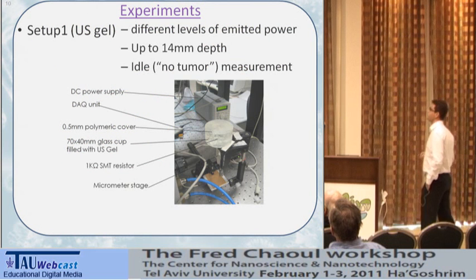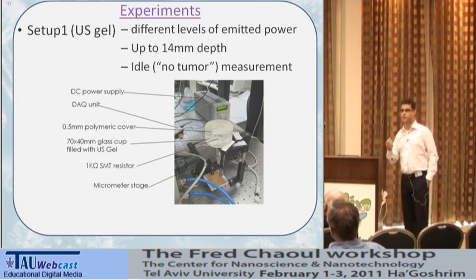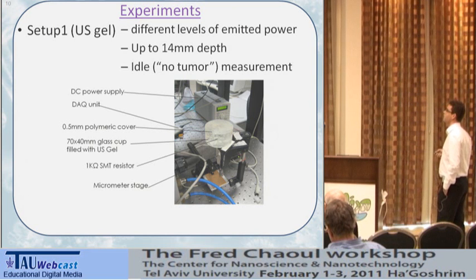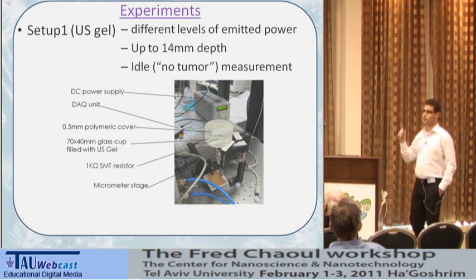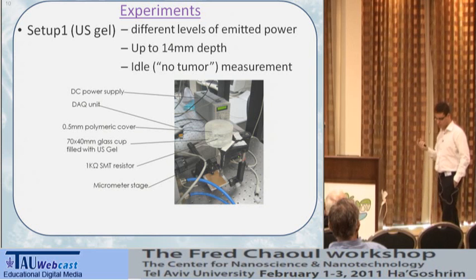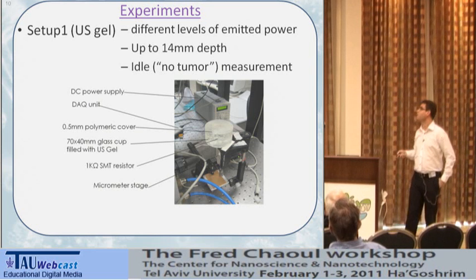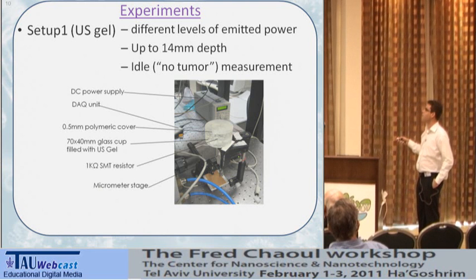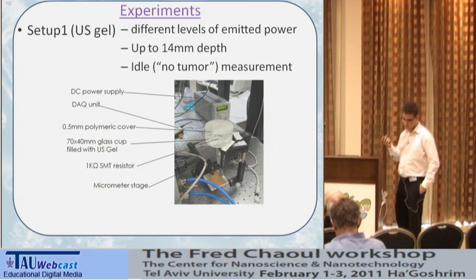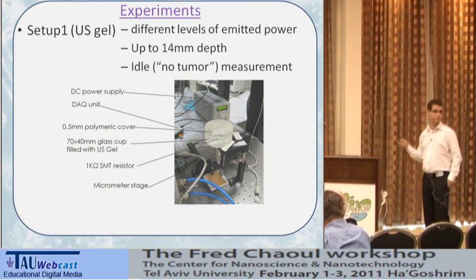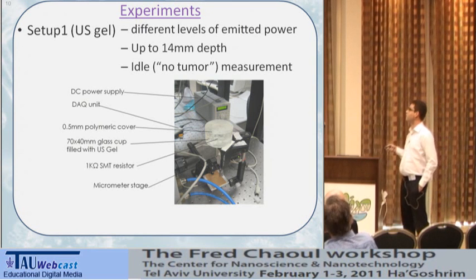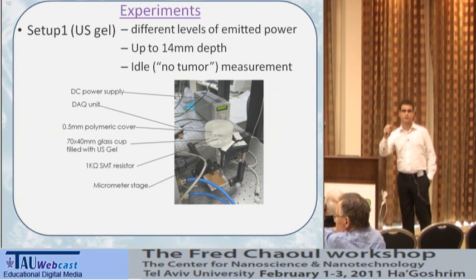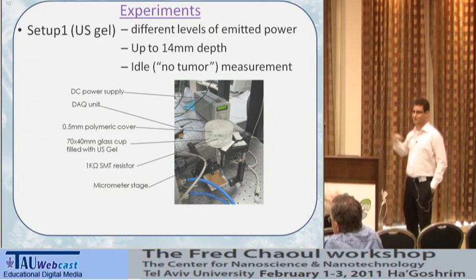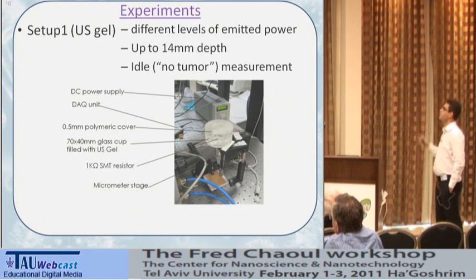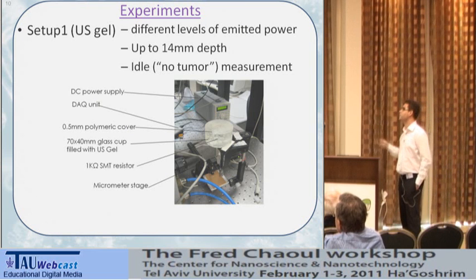So to test this algorithm, we did a series of experiments. In the first experiment, we wanted to be very controlled, very precise. So what we did, we put a controllable heat source inside ultrasound gel, which mimics the tissue thermal properties. And we also put a polymeric cover here on the top of it to simulate the skin thermal resistance. And we took pictures with the IR camera, of course. And this way, we can control exactly the location of the heat source, and we know how much heat is dissipated because we control the source. And we can train the algorithm with this setup.